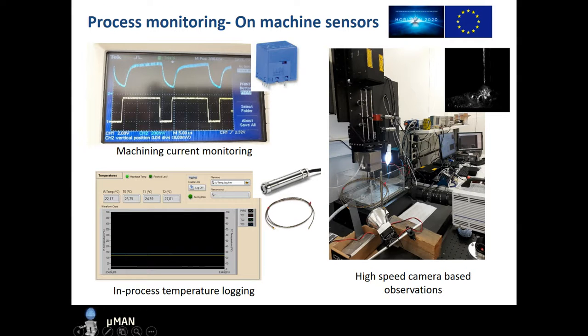In the framework of the Microman project, we also do some inline metrology on our machine. We have a Hall current sensor to monitor the process current. We also have temperature measurement devices on the machine to record the temperatures close to the machining zone. And we put a high-speed camera close to our machine to see what is happening in the gap when the laser is hybridized with ECM. In ECM we have hydrogen bubble generation and gas evolution, but when we add the laser, these rates are expected to increase. We are going to study this with high-speed camera-based observations.